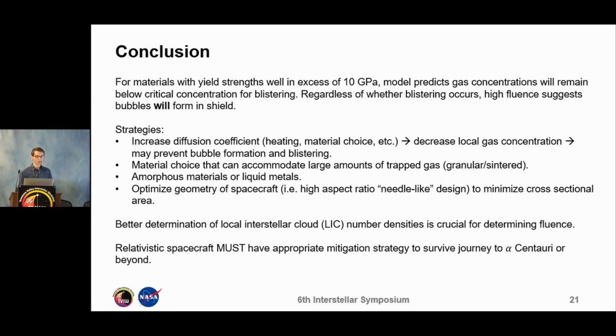A material choice that accommodates a large amount of trapped gas would also be useful, something that's granular and sintered. Amorphous materials or liquid metals would be useful to discuss or to look into further. And you can also optimize the geometry of your spacecraft to minimize the cross-sectional area. So a needle-like spacecraft would also be useful for this purpose. Similarly, a better determination of the local interstellar cloud densities is crucial for accurately determining the fluence that a spacecraft will have to endure. And the largest takeaway from all of this is that a relativistic spacecraft must have an appropriate mitigation strategy to survive a journey to Alpha Centauri or beyond.